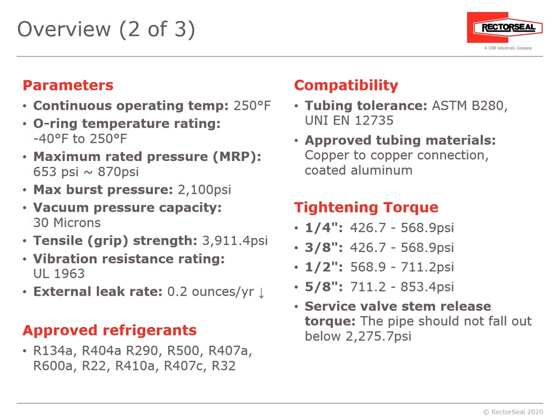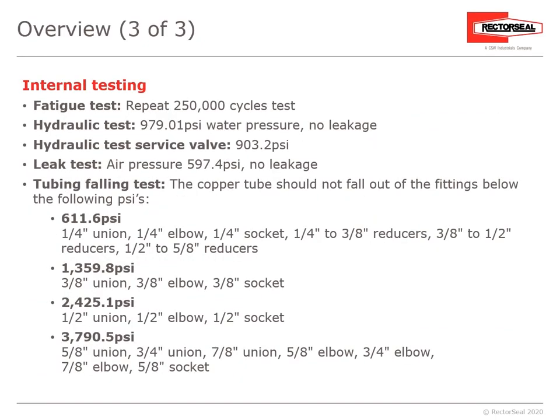For compatibility, it's tubing tolerance according to the ASTM B280, the approved tubing materials, copper to copper connection, and the coated aluminum. The tightening torque is going to vary by diameter. For the 1/4 inch and 3/8 inch, the tightening torque is between 426.7 to 568.9 psi. Half inch, 568.9 to 711.2 psi. And the 5/8 inch between 711.2 to 853.4 psi. And the service valve stem release torque, the pipe should not fall out below 2,275.7 psi. And then internal testing that's been conducted within RectorSeal, a fatigue test, a repeat 250,000 cycles test.